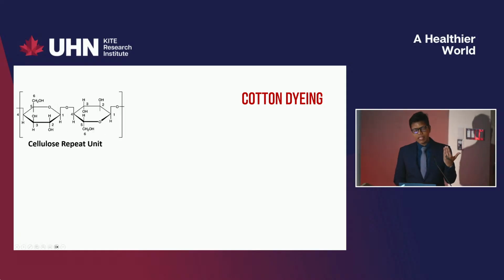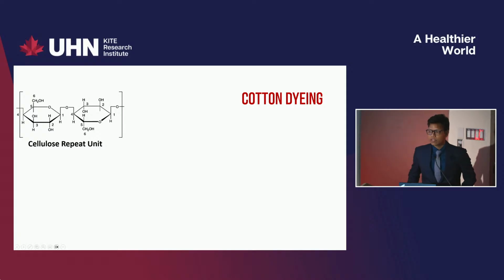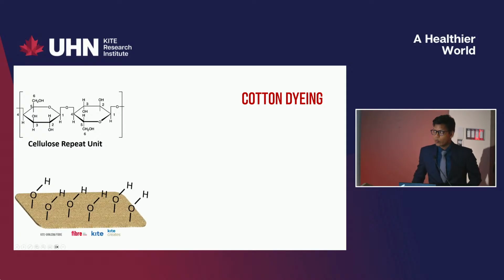So I'll start with the cotton dyeing process. And in the beginning, I was mentioning that whenever we are talking about dyeing, we want to bond the dye particles with the fiber itself. So the fiber chemistry matters a lot. If you look at the cellulose repeat unit, which you can find in the cotton fiber, you see cellulose has a lot of hydroxyl groups. So we want to activate these hydroxyl groups.